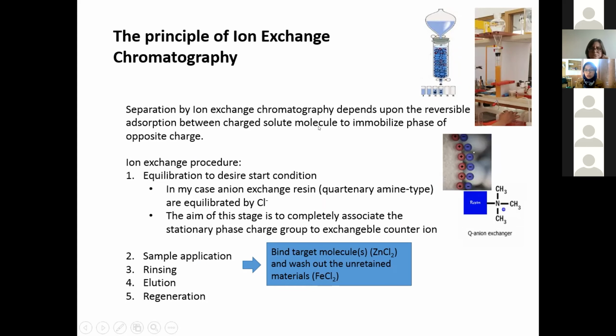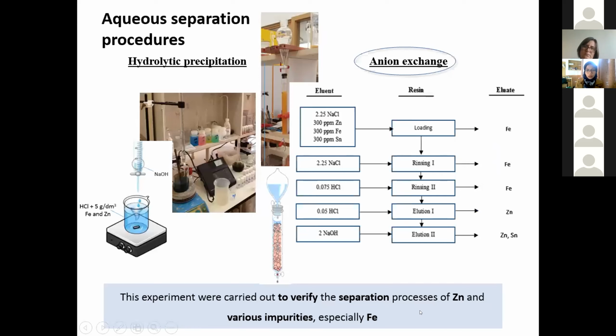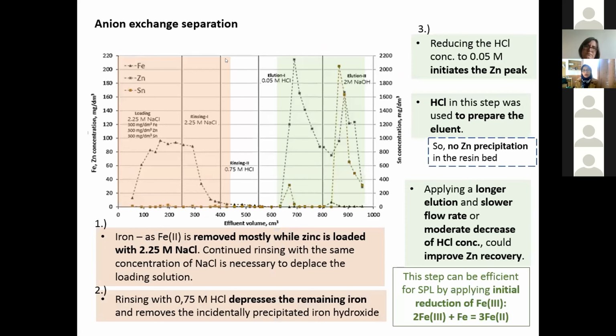So here we use an immobilized phase, the quaternary amine, which we equilibrate with hydrochloric acid, where the chloride ion is used as the ligand that will make a complex with the zinc, and then the iron will go through the column. And this is the process where we use rinsing, elution, and another elution to make sure that all the iron is out from the column before we take out the zinc to separate it. So here we can see that the iron can be separated from the zinc.